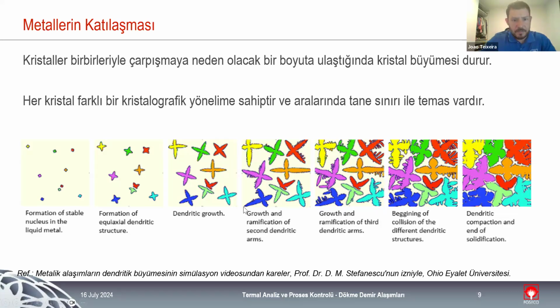What we have here is the scheme for all types of ferrous and non-ferrous solidification. So this type of solidification is the same, whether we are dealing with cast iron, aluminum alloys, or brass alloys. The basis of solidification is the same. Stable nuclei, growth, and grain boundaries at the end. And this solidification always happens the same way. As you can see here, these are what we call dendrite branches. And these dendrite branches start to go against one another and they start to solidify together. And this type of solidification happens in all ferrous and non-ferrous materials. So it's the same, whether we are dealing with cast iron, aluminum, or brass alloys. The bases are always the same.